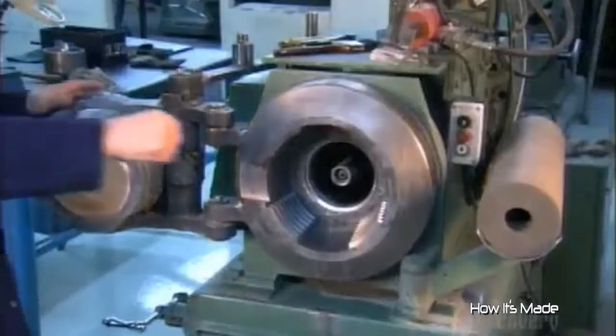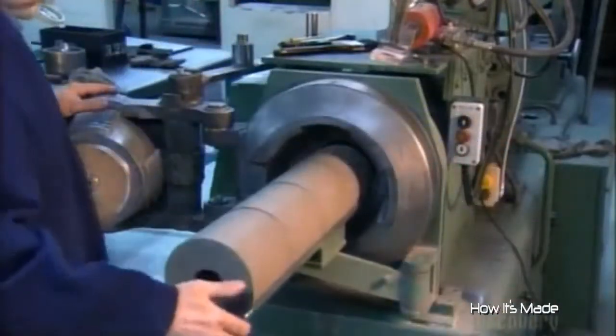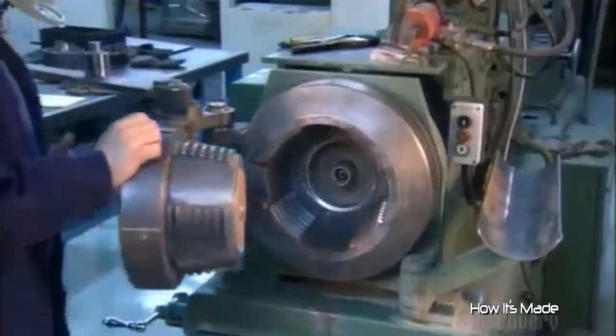Now to put the powder coating on the core wires. A worker loads four slugs into an extrusion press. It'll apply 120 tons of pressure on the slugs to shoot the powder through nozzles that'll coat the wires as they pass through the slug's hole.